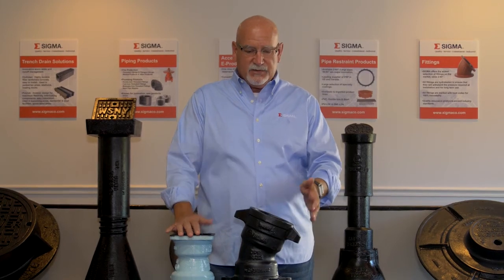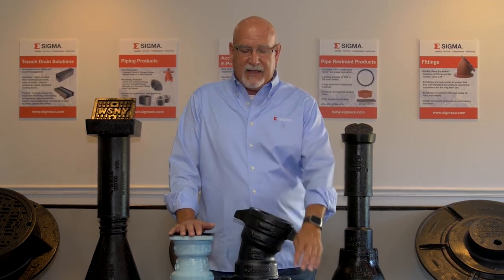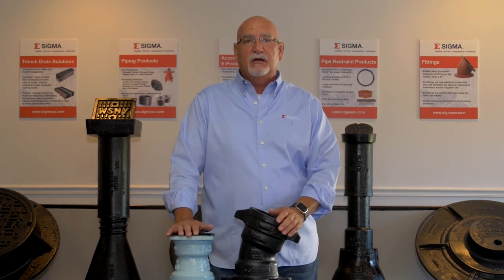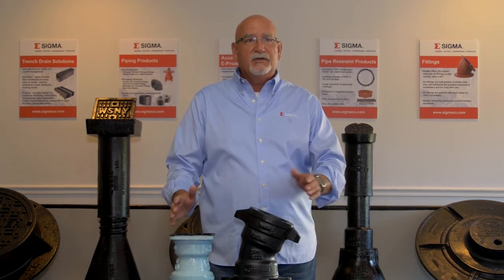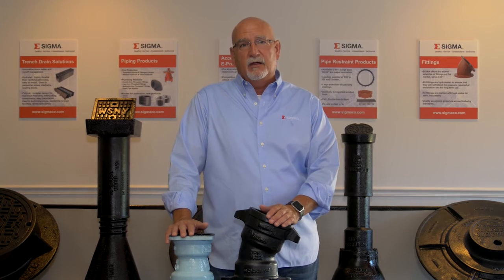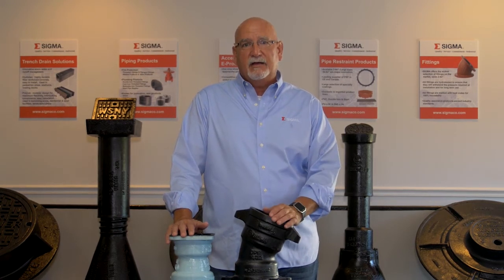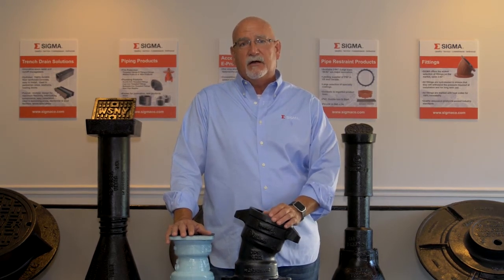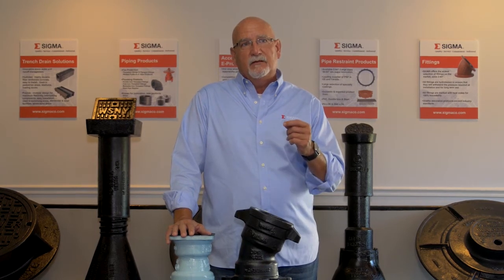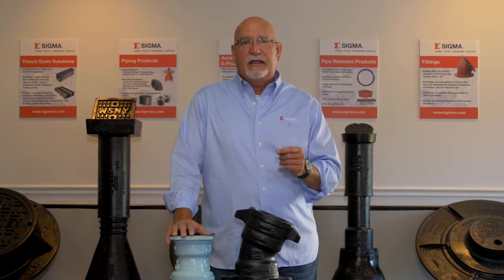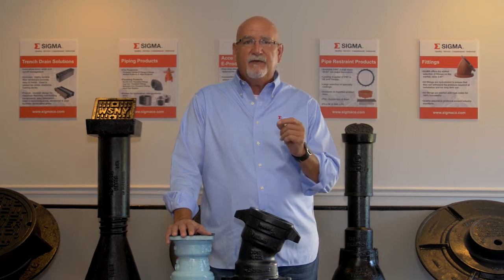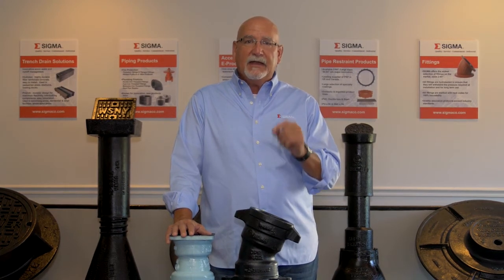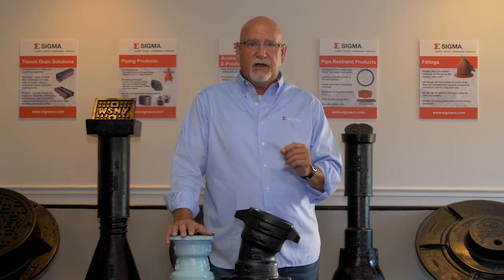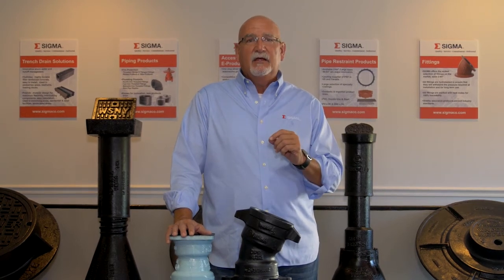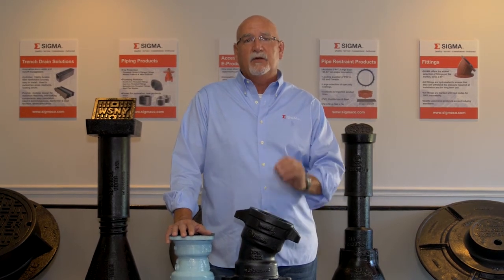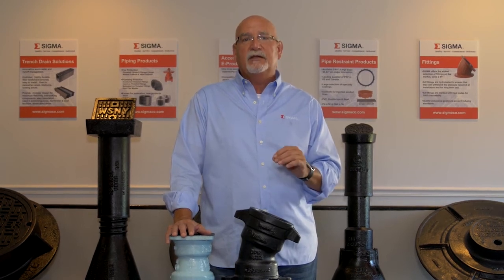So when we do side-by-side comparisons of our CoreSafe against the other materials that are available in the market, we find that our coating actually performs better because the likelihood of having a small defect in the coating on any process other than E-coating is very high. And that small defect creates a localized spot where corrosion happens very quickly.